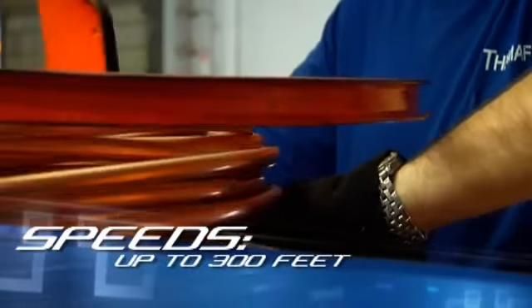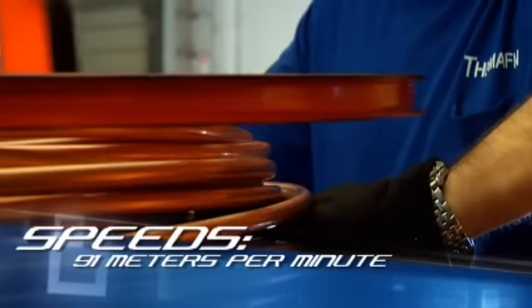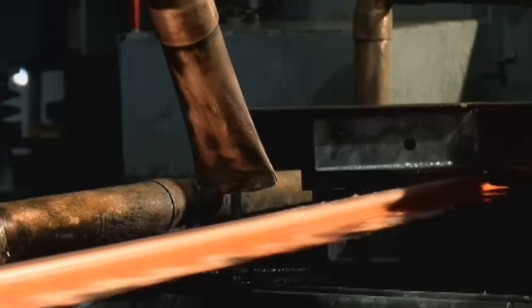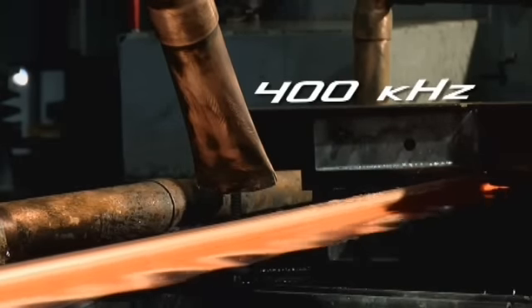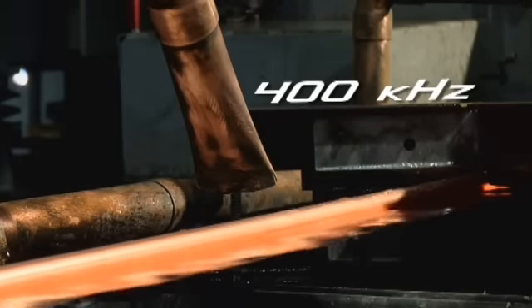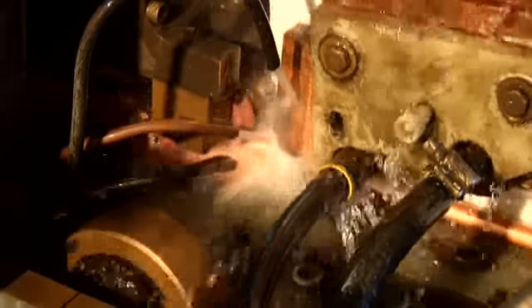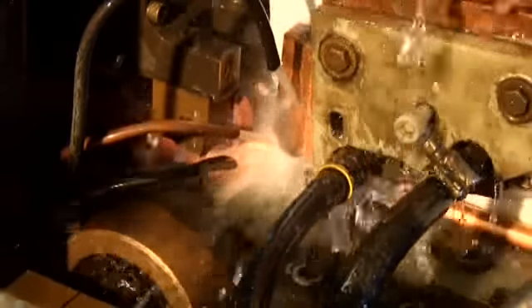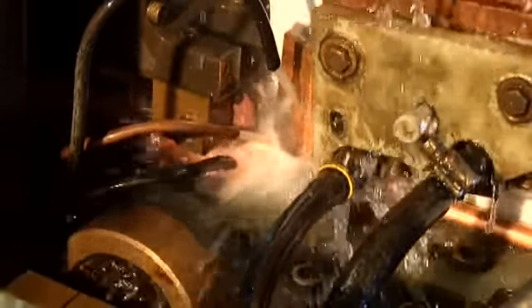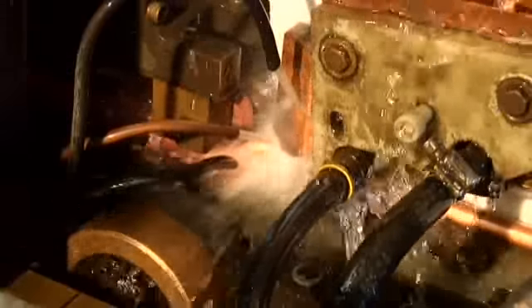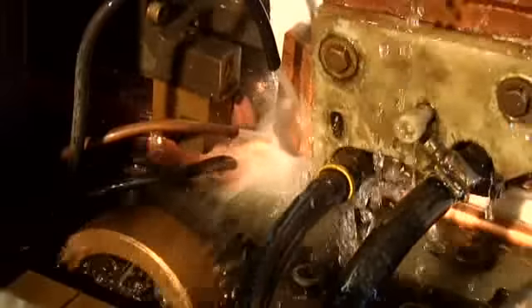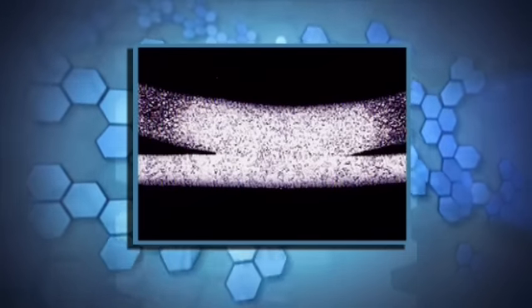Capable of welding speeds of up to 300 feet or 91 meters per minute, the welding line delivers a high-frequency 400 kilohertz for various tube sizes and fin widths. The weld zone is a minimum of 2 times the thickness of the copper fin, providing the most efficient heat transfer possible and ensures a deep molecular bond guaranteed for 30 years. Cross-sectional microanalysis shows grain structure throughout the weld zone without fractures or inclusions.